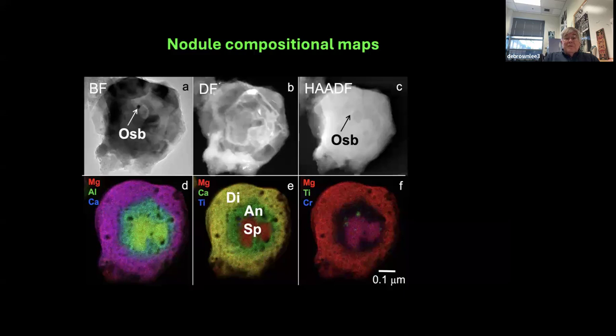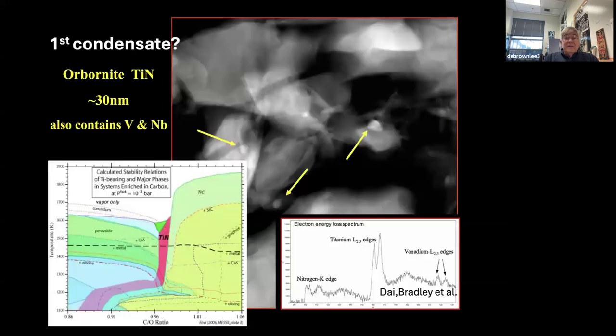These are just some maps of the built-up nodules. These are really small ones, but you can see their diopside around anorthite with spinel in the core, and a little green dot in the lower right-hand corner pointed to by arrows is osbornite, which is titanium nitride.